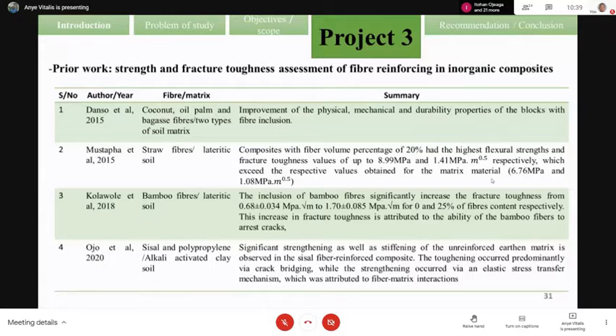Later on, Kolawole has studied the bamboo fiber reinforcing lateritic soil material. I realized that by using 25% of those bamboo fiber, we can increase the fracture toughness and the flexural strength, and the fiber will behave as a crack arrestor in the material. Later on, OJ studied sisal and polypropylene fibre in alkali activated clay soil, and realized that those fibers were helping to improve the strength and the fracture toughness, and the predominant mode of rupture here was crack bridging.